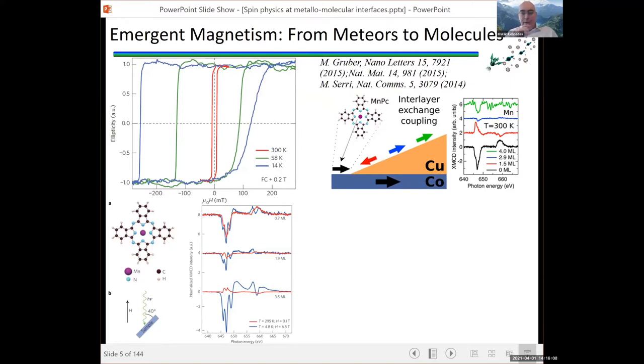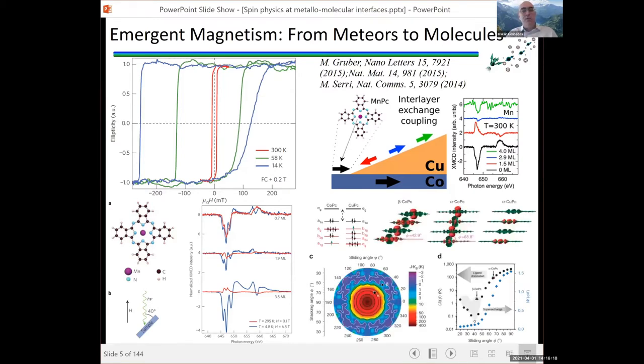Then from the group of Sandrine Heutz at Imperial College as well, they also studied the magnetism of the phthalocyanines, in their case cobalt phthalocyanine rather than manganese phthalocyanine. And what they found is that depending on the stacking of the molecules, whether it's beta, so higher angle between the molecules, or alpha, so not quite flat, but mostly flat, you could have a different magnetic arrangement.